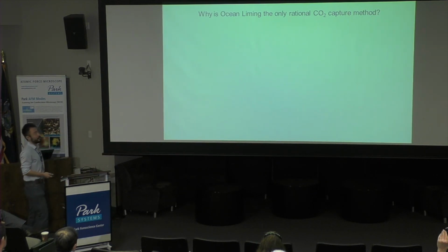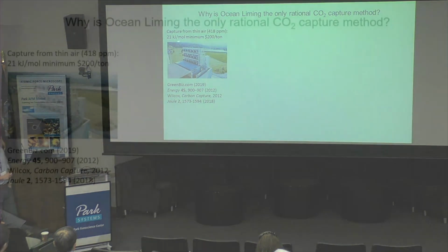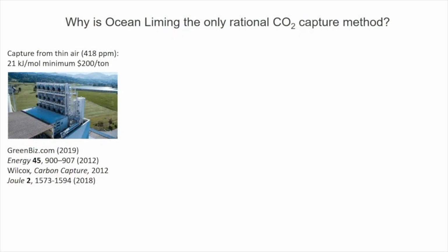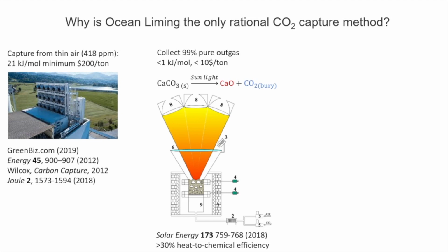So it's obviously feasible. All right, so I really want to reiterate the point of why ocean liming is the only rational CO2 capture method. This sort of filter in the air is basically capturing something from thin air, 418 ppm. It costs theoretically a minimum of 21 kilojoule per mole, corresponding to $200 per ton, to capture CO2 this way. When we capture directly from a solar furnace that's producing CO2 from the decomposition of calcium carbonate, we have a 20 times or more efficient process energetically and economically.